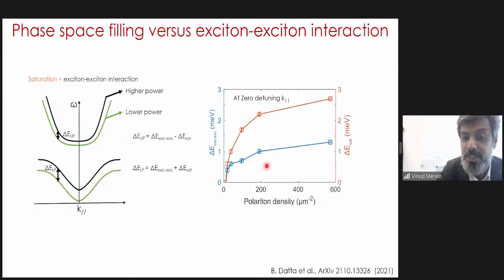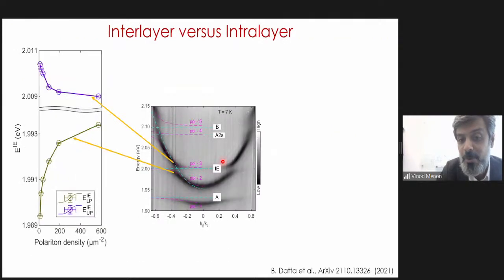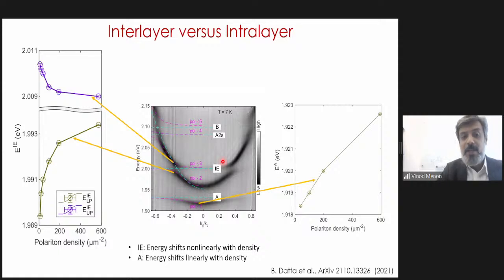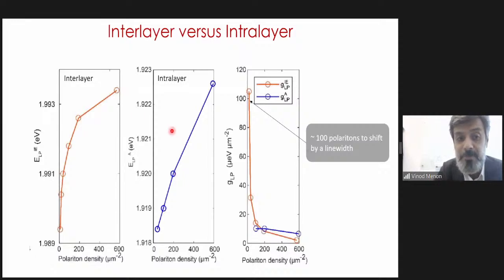So what we see is that in this case, at low polariton densities, the two processes become comparable. But what we're really interested in is to ask the question, how much shift do we get in these line widths if you put in a certain number of photons? What we really want is one line width shift for one photon. That's our ultimate goal. But let's see where we are. So you will see that this is the interlayer, this is the intralayer, which is the A exciton. And at these very low densities, you need about 100 polaritons to shift by a line width. So again, we're still in the classical limit. We haven't got to the quantum limit of few photons.